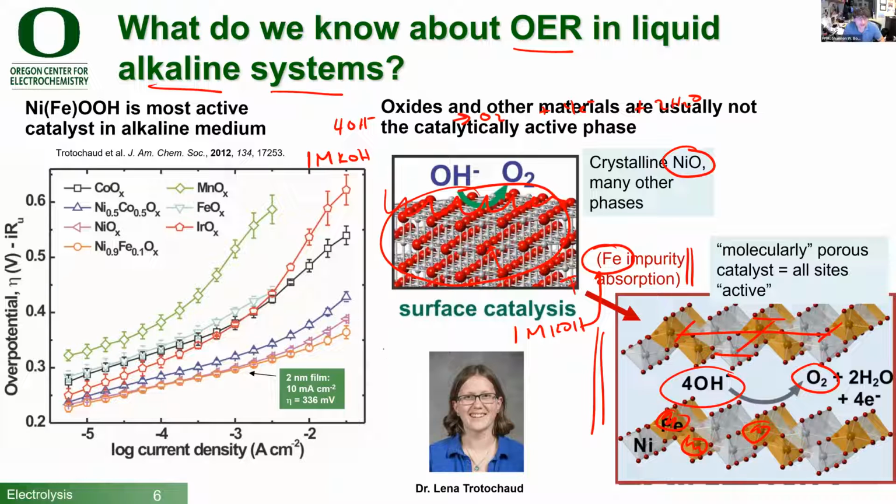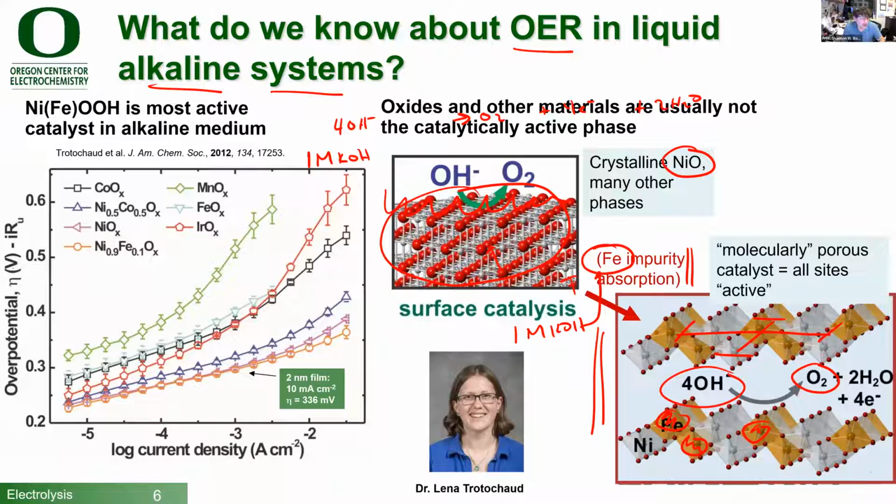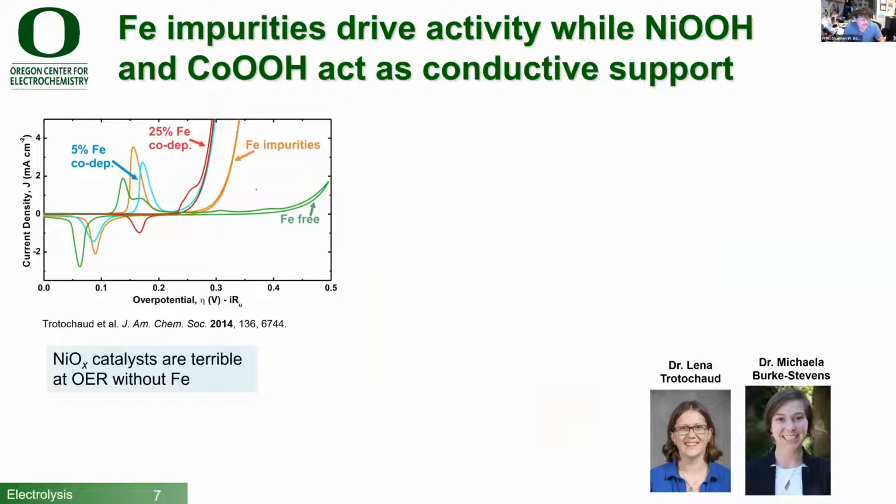But one thing we found is that the catalysts that are good at this all have nickel, cobalt, and iron. Nickel or cobalt and iron. And they all form these active phases at the surface to varying degrees. And the effect is pretty substantial.